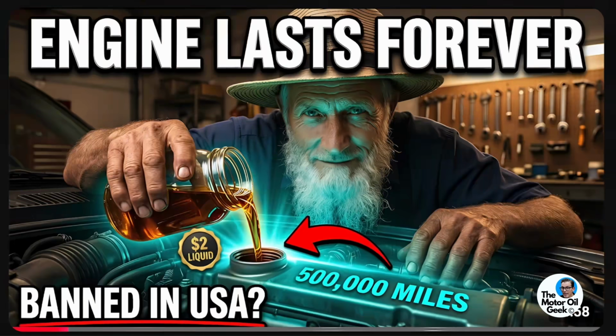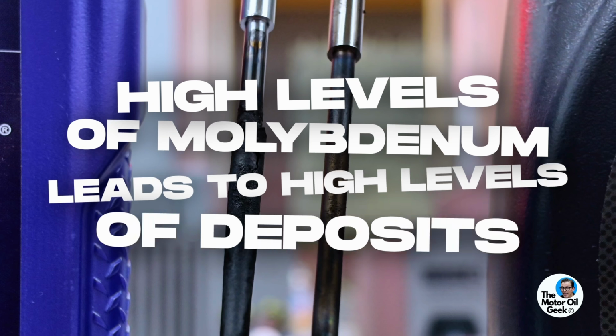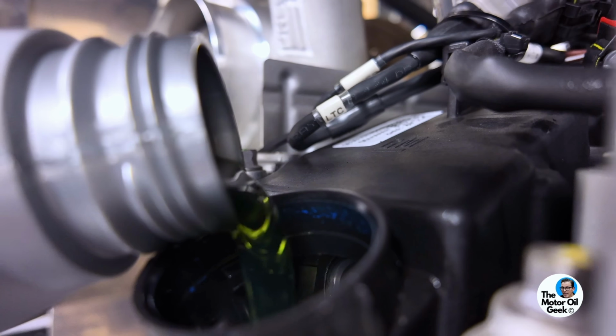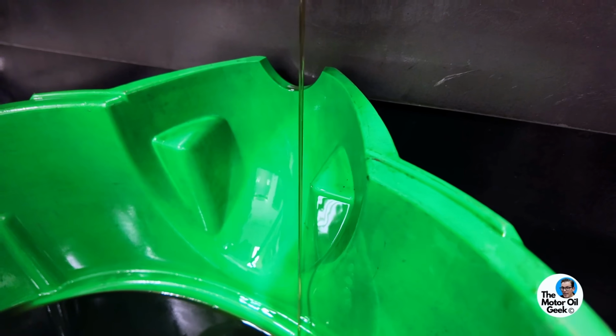Warning: despite the misleading claims made by a couple of viral AI-generated videos, adding molybdenum disulfide, MoS2, to your motor oil doesn't make it permanently adhere to the metal surfaces or make your engine last forever. In fact, the opposite is true. High levels of molybdenum tend to lead to high levels of deposits. We're going to show that in an upcoming video. Also, as soon as new oil without the MoS2 is added to the engine, the detergents wash all the moly away, and high levels of molybdenum actually increase wear on DLC-coated engine parts.